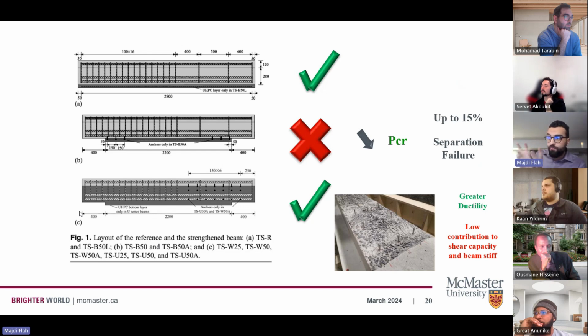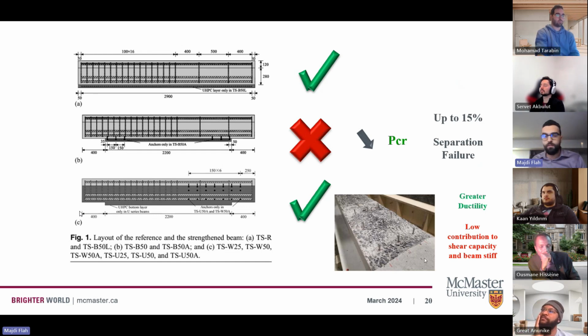So the authors tried to investigate that behavior as mentioned here, and they found out that the cracking capacity decreased up to 15%, and we started having a lot of separation failures in that area. So for that reason, they tried to put some shear studs in order to improve the behavior. But even with the shear studs, there is a very low contribution to the shear capacity and beam stiffness. Bearing in mind, we have a greater ductility in that situation.